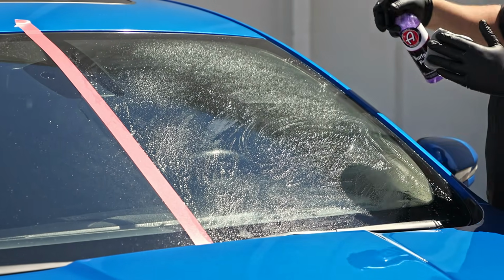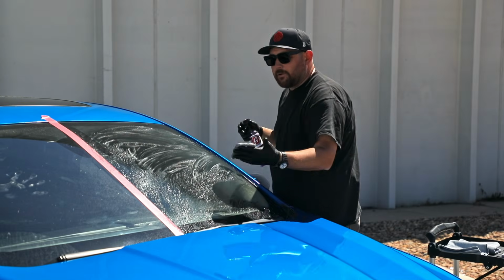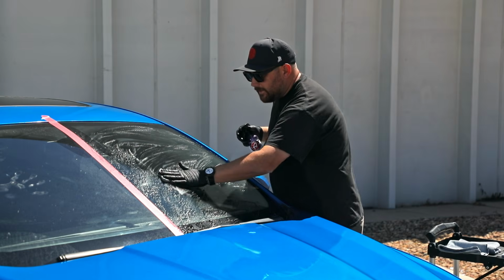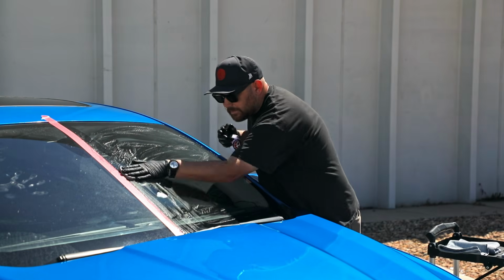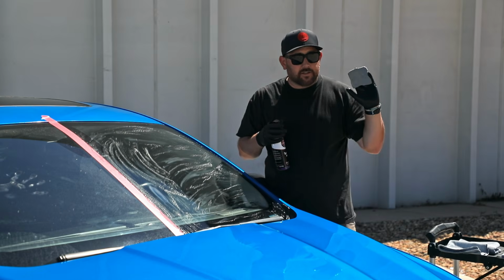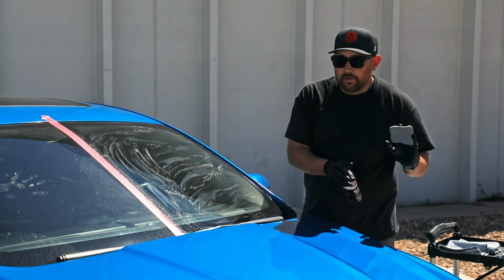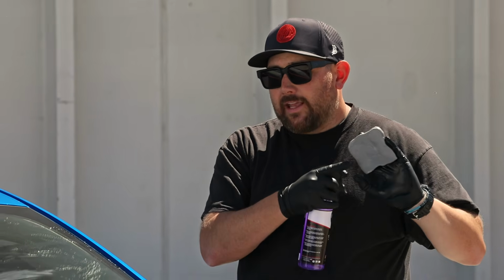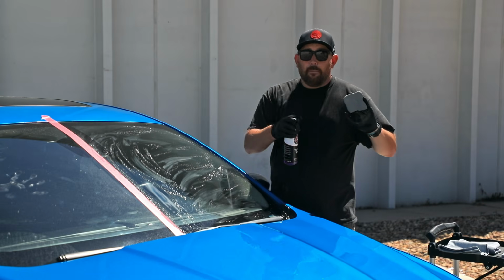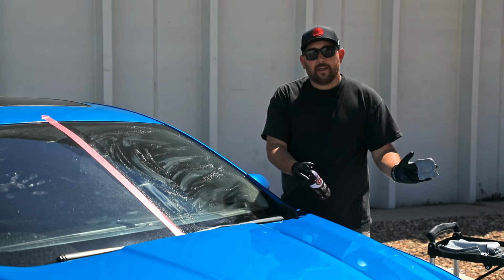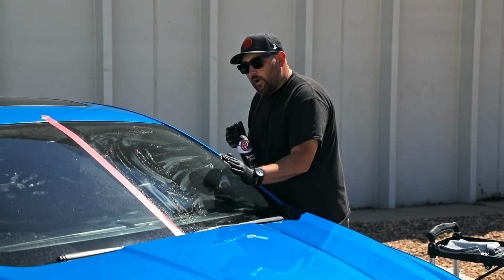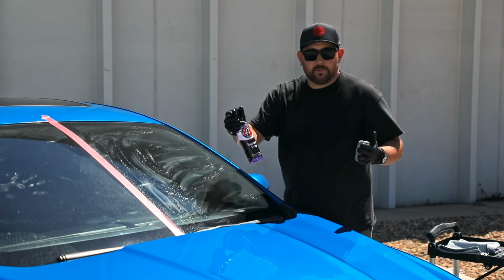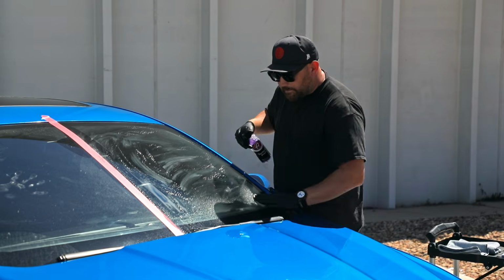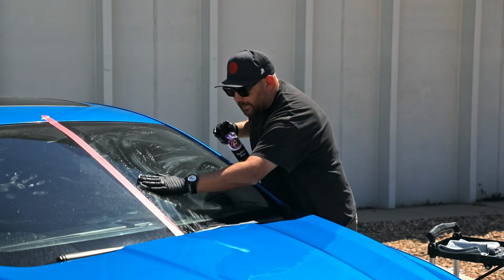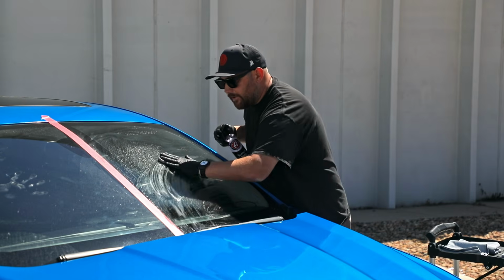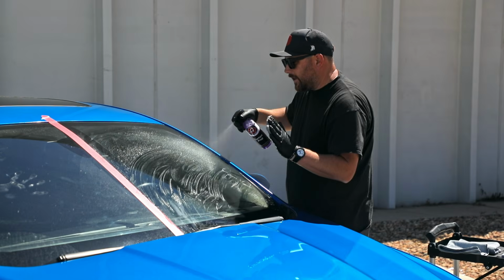But in this case, the medium grade clay bar is perfect for claying your glass because the medium grade clay bar can actually mar the painted surface, like your clear coat, just a little bit. This is usually dedicated to the process before you paint correct or machine polish your car for the paint. But glass is different. It's not going to mar the surface of the glass. It's a much harder surface than clear coat. So I actually prefer using the medium grade clay bar to clay glass rather than a fine grade. It does more work with less effort.